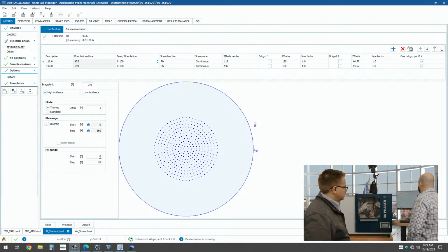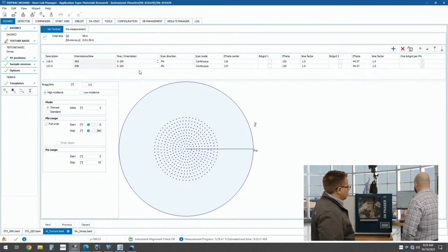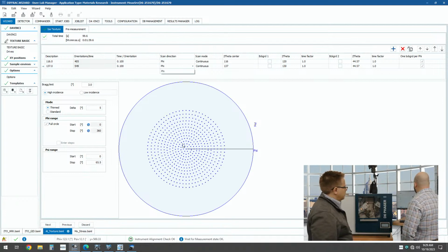And then, of course, the psi range is set automatically based on that. So it's actually very easy to set up. And you can see that you do get pretty good coverage. With these higher order, if I go even to this angle, you see we get even more coverage. So the higher the angle, the more coverage you're going to get.